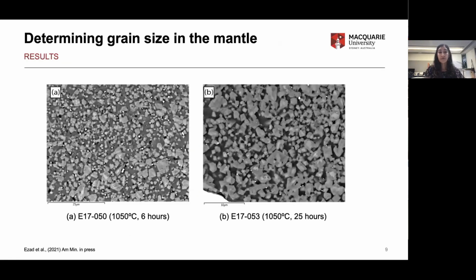So upon retrieval of my experiments, I did the usual set of analysis, which involved embedding these in resin mounts, polishing them to a mirror finish, and then I imaged all of my experiments on a field emission SEM at Cardiff University. And qualitatively, we can see that from a period of 6 to 25 hours, there is an increase in the grain size, and that's what we were hoping to see. In this image, these cuboidal or kind of square-shaped grains are the spinel grains. The background material is orthopyroxene.